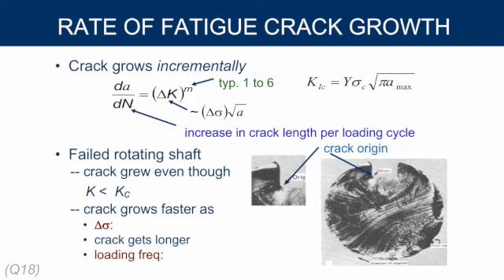Okay, so the whole idea is that cracks will grow incrementally. We're adding energy to the system when we put a force through a distance on a material. That energy has to be dissipated. Typically, that is dissipated through crack growth. Or the other way would be for the radius of curvature of the void to expand. That would dissipate the energy as well, and that would be a material that can self-repair. But in most cases, we get crack growth, which causes failure. Okay, so let's take a look at this.